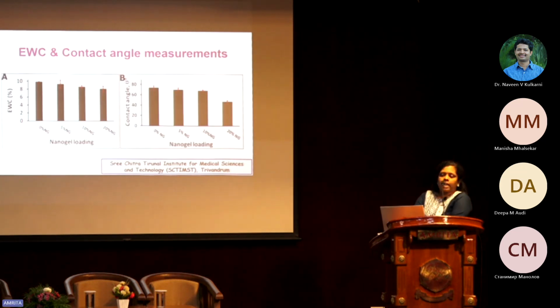And then we have checked the equilibrium water content and contact angle measurement of the system in order to see how this nanogel composition in the base matrix will affect its bulk properties. We can see that for equilibrium water content there is no significant difference, but still a slight decrease. That shows that the hydrophilicity of the system is slightly decreasing. That is mainly because the cross-linking density of the system is increasing because of the reaction of this reactive nanogel with the polymer matrix. And also the contact angle. These two, equilibrium water content and contact angle, are somewhat contradictory, but the contact angle may be decreasing, or the hydrophilicity increasing, after introducing the nanogel, because we are introducing the thiol functionalized nanogel. The hydrophilic thiol group is introducing hydrophilicity on the surface of the material. So that may be the reason it is decreasing.